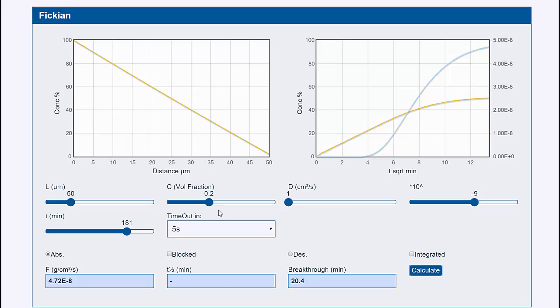In the experiment, you dunk it in, and every so often you pull out the sample and weigh it. And if you are lucky, then after your three hours, you find that you've reached more or less 50%. You've just reached the equilibrium value you expect from Fickian diffusion.